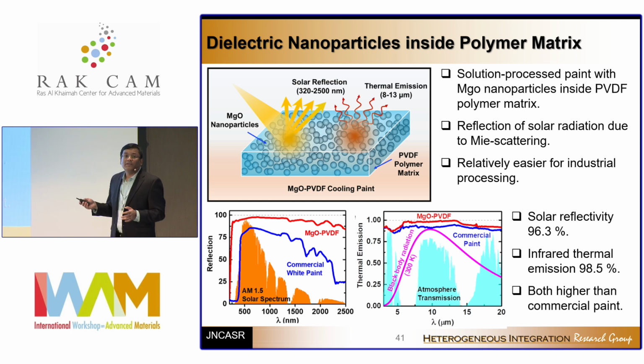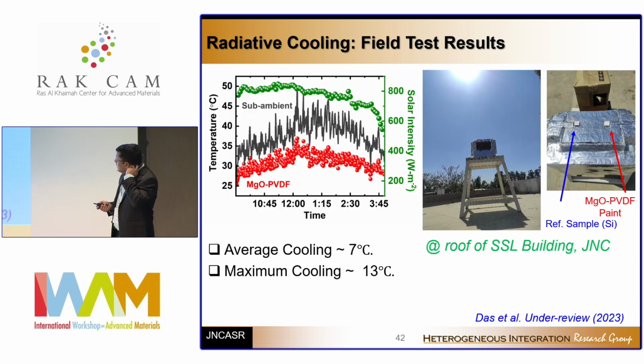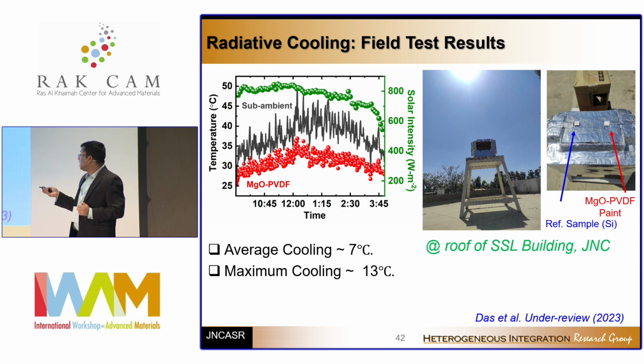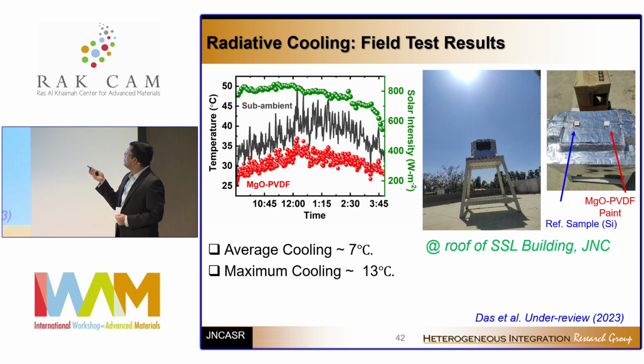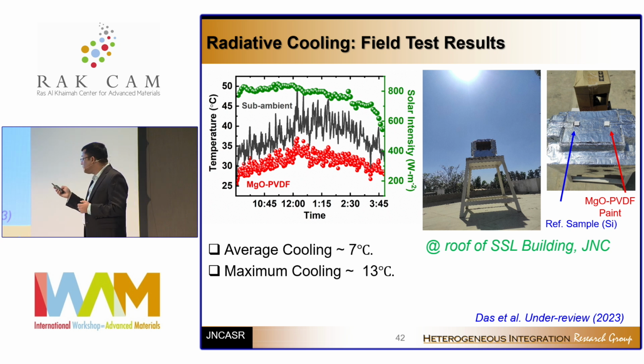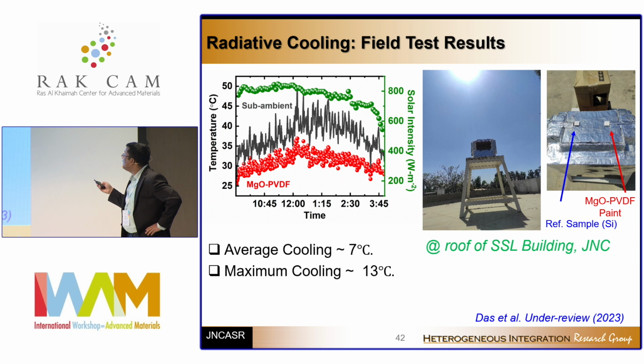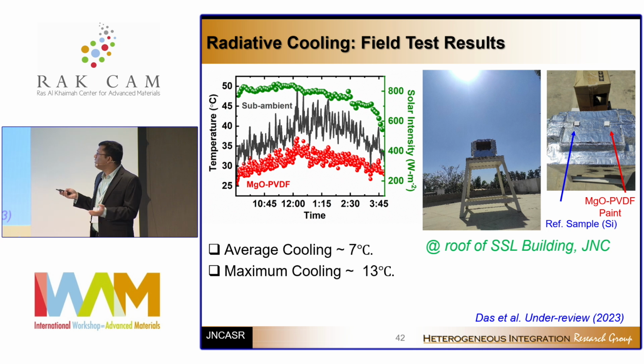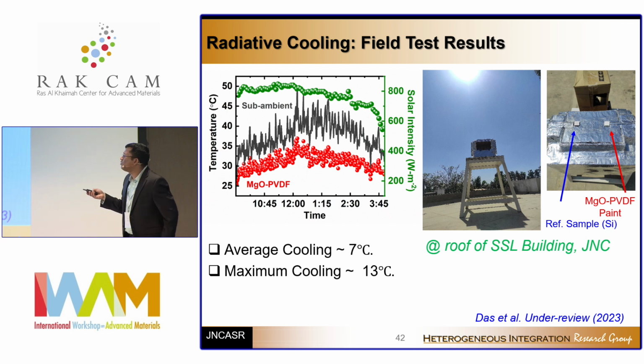Now, does it work in real life? That is what I want to show you. This is a real-life experiment done at the Sheikh lab in JNCASR on the terrace of it. We have two samples, one is the real sample, one is the reference sample. We first tested what the cooling efficiency is between a reference sample and a real sample. The top one is the solar intensity on that particular day, and this is time. We started to measure at 9 o'clock in the morning and ran it up to 4:30 p.m.